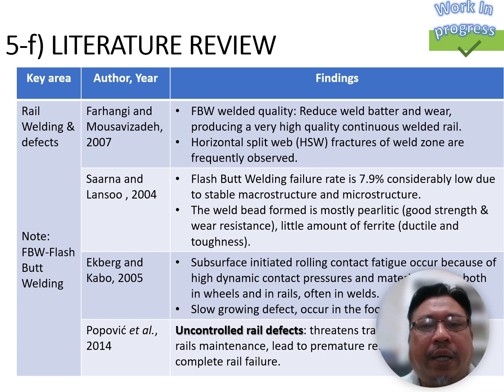On the literature review, there are many references in relation to the defects of welded rails and surface crack initiation. Farhangi and Mousavizadeh 2007 concluded that even though flash butt welding is superior in quality compared to aluminothermic welding, flash butt welding still has failure issues due to horizontal split fracture. A second reading is by Saarna and Lansoo 2004, who found that even though flash butt welding failure is low at 7.9%, most of the studies found that failure to remove the underlying surface crack will cause the crack to propagate. So if we don't remove the underlying crack, it is going to propagate and contribute to the rail breakage.